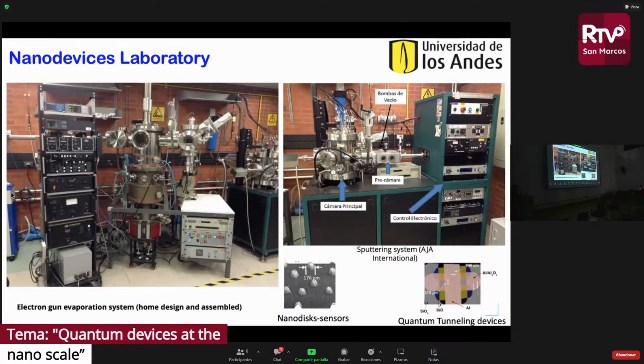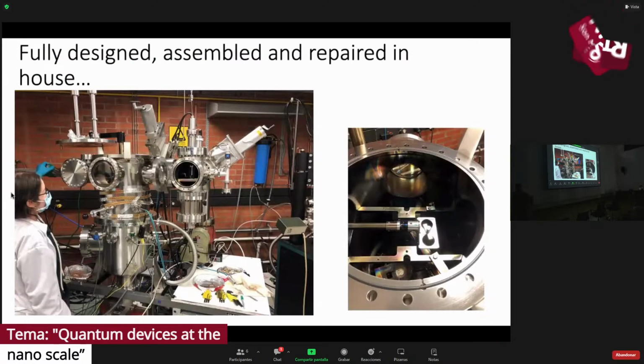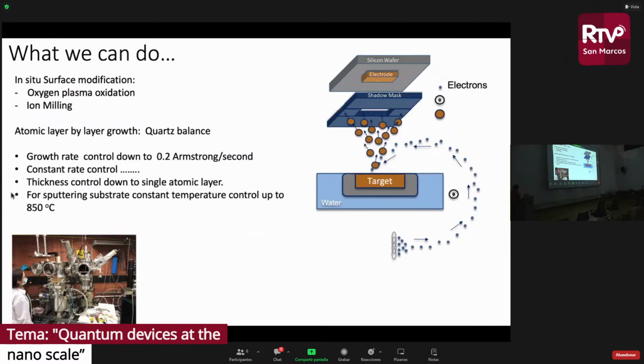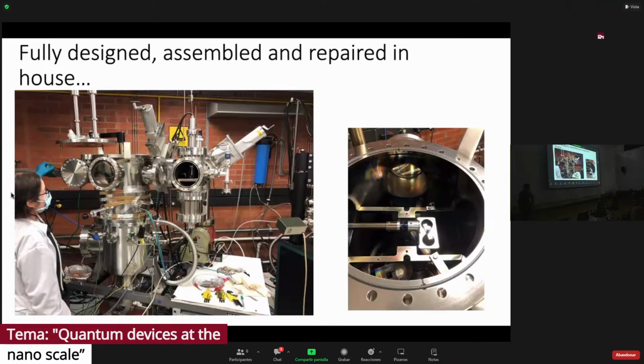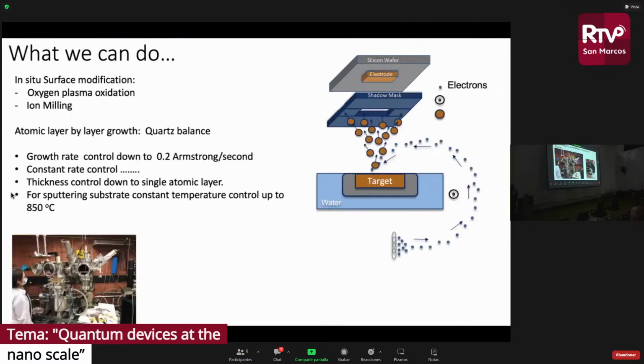And the other one is the sputtering system. That's a commercial one, but we also make modifications. The sputtering system is for other processes, for sputtering and co-sputtering. And here you can see one of my students disassembling the system, because it's important to be able to modify things within the experiment in order to have new results. So we focus on making modifications, which normally in commercial systems you don't have the possibility to do. This system has a number of capabilities that allow us to make ultra thin, ultra pure materials in the ultra high vacuum regime. We can reach pressures of 10 to the minus 9, 10 to the minus 8 millibars. That makes it a good system for applications.